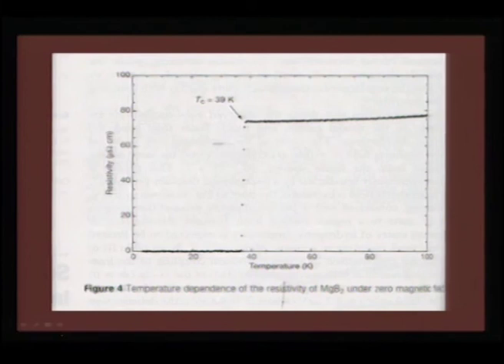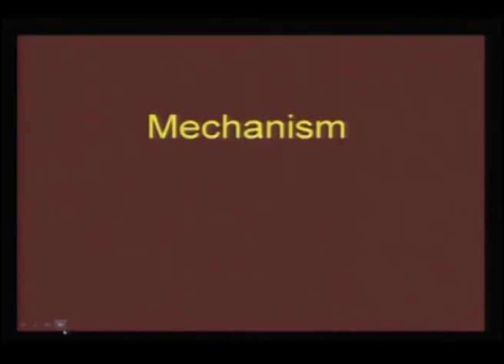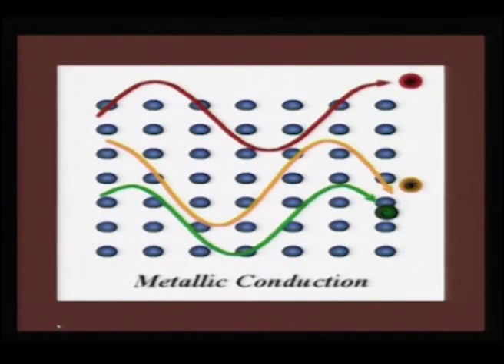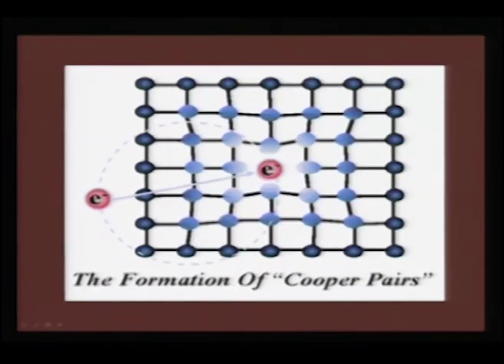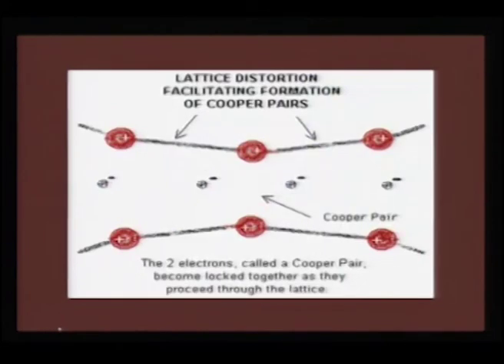Therefore, the game has always been a serendipity as far as superconductivity is concerned, and this is the Tc curve which clearly shows a 40 K superconductor for magnesium diboride, and the mechanism is based on metallic conduction. You would see electrons going through the lattice with minimum scattering, but what really governs the superconductivity is the formation of Cooper pairs, and these Cooper pairs really govern the issue of superconductivity.